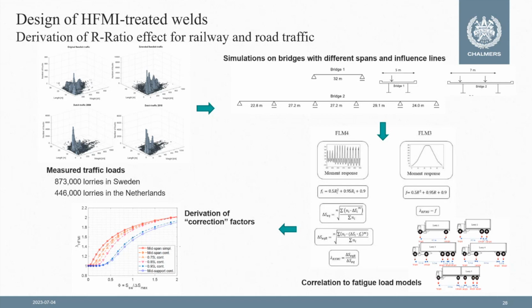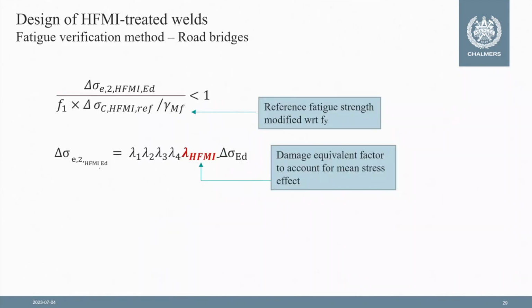So it's similar to lambda 1, for example, that is used in the simplified fatigue design in the Eurocode. So the fatigue verification format is very similar to the one that we have for the as-welded detail. Delta sigma E2, now HFMI, of course, is the equivalent stress range at 2 million cycles. This is related to the fatigue resistance, HFMI, modified with the factor F1, which takes into account the fy effect. And the R ratio effect is now put on delta sigma E2, similar to lambda 1, lambda 2, lambda 3, with a new lambda factor, which is lambda HFMI. And this lambda HFMI was derived from these traffic measurements that I mentioned before.